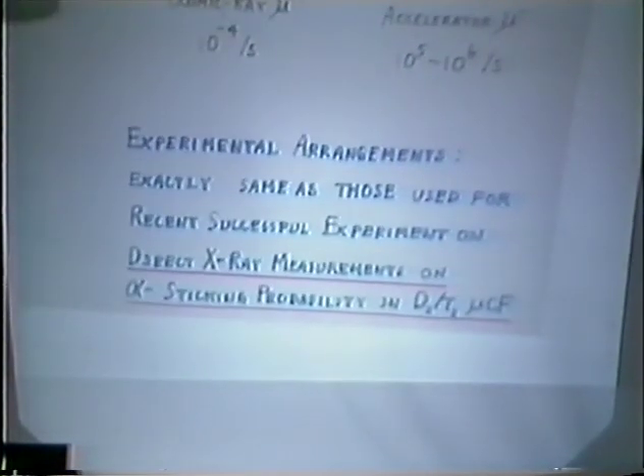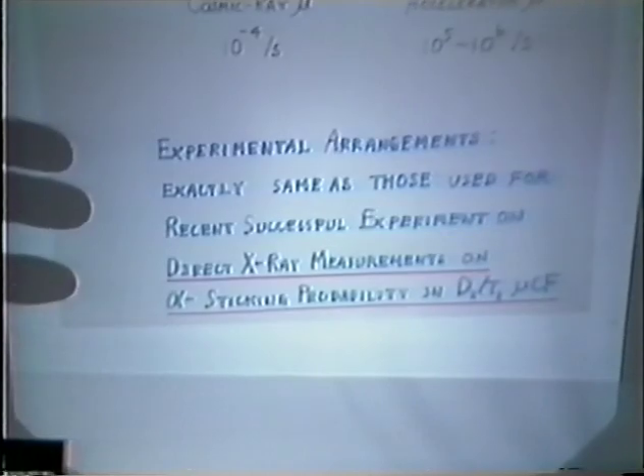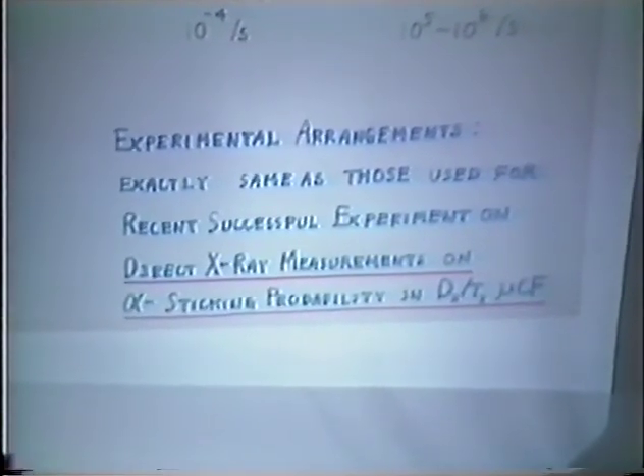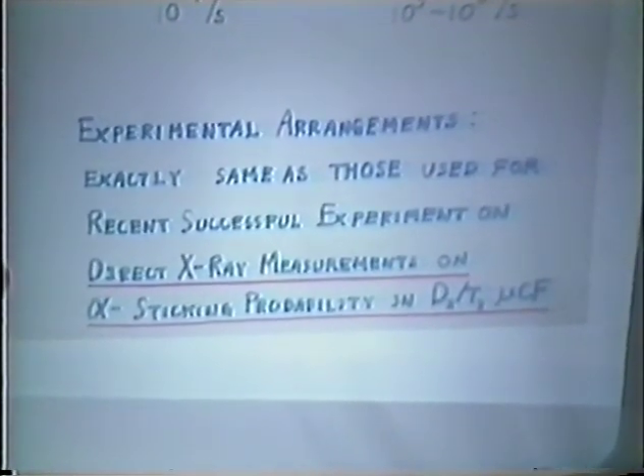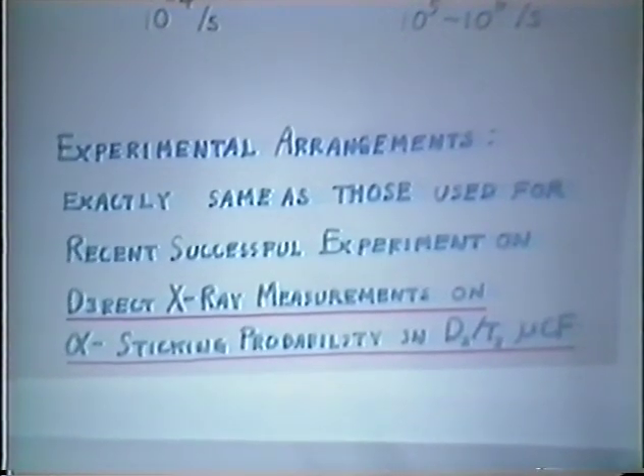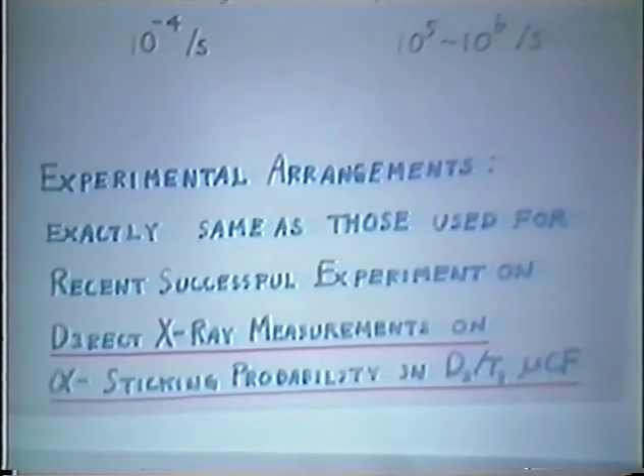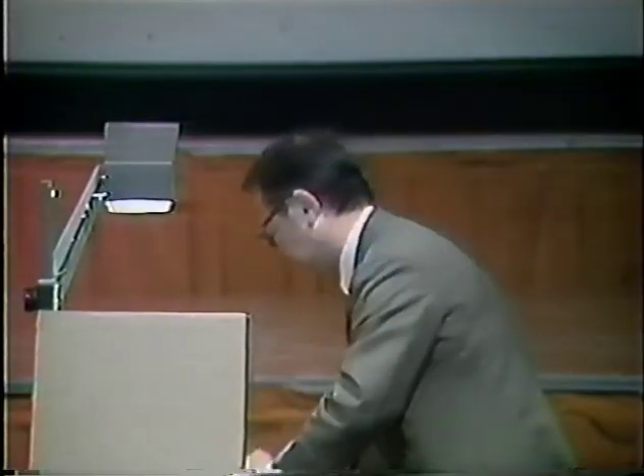The experimental arrangement is exactly the same as those we used for the recent successful experiment on the direct X-ray measurement of alpha sticking probability in high density, high tritium concentration D2T2 muon catalyzed fusion.